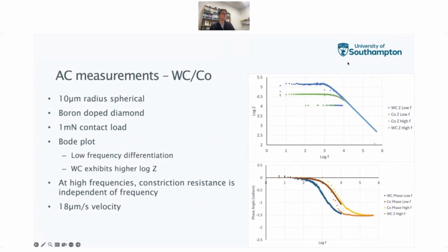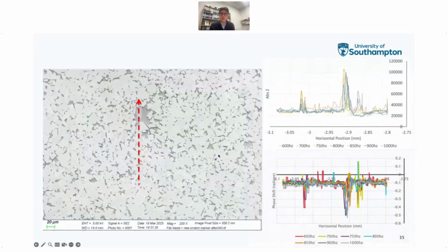So for these Bode plots, we've got the tungsten carbide in the blue and the cobalt phase in the green. And we can start to get a little bit of discrimination with the log impedance value there between the two phases, especially at the lower frequencies, not so much at the higher frequencies, but also in the phase angle as well. So then from that, we can move to perhaps sliding across the surface and seeing if there are frequencies that respond to the different phases that are present. So we've taken a number of traces across the tungsten carbide cobalt cermet along this red dotted line here, and we varied, just as an example, a number of frequencies, and we're getting a different response at different positions, both in the absolute value of the impedance and also the phase angle shift that we have there.